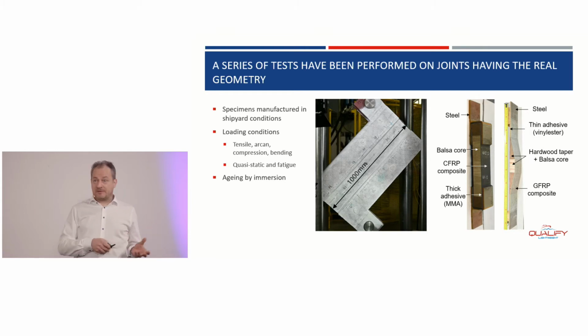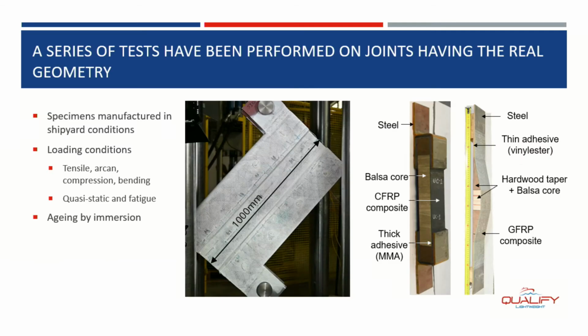So then we have to transition to a component level, to joints that are representative for joints in the real scale. At the left of the slide, you see on the one hand the Damen joint, the darkest colors and thick composite panel or sandwich panel of composite plates on balsa core with steel brackets. On the right, you have the BAE specimen with a very thin adhesive layer of vinyl ester.